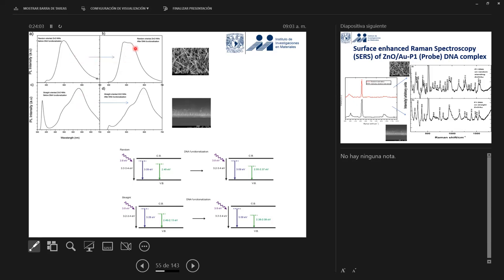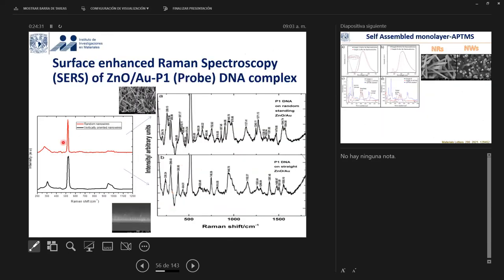There were some changes in the response, and the intensity also changed. In this case, we have normalized the spectra, so you cannot see the differences in the intensity, but you can appreciate the difference in the bands in the final emission of the structures. So we found that there were some changes in the emission spectra after functionalization. There were some changes in the band levels, in the energy levels, which were responsible for the final emission response of these one-dimensional nanowires. We went further, we did Raman studies.